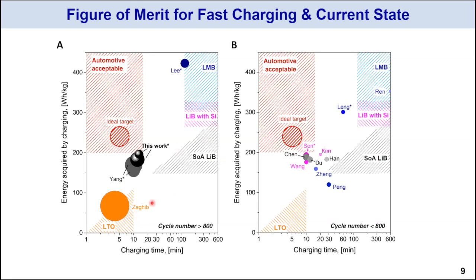And then in addition, you see three groups of data here. And this very gigantic orange bubble basically is the LTO battery. As expected, very durable, and you can cycle many times. You can charge in less than 5 minutes. But again, unfortunately, the energy density is a little low. And then you have here a bunch of graphite-based lithium-ion batteries making steady progress and starting to enter this automotive box for the very first time. So I will explain a little bit more detail shortly about this group of research.